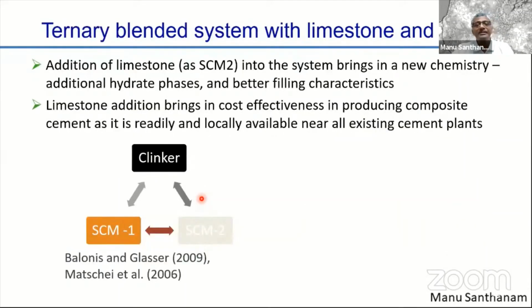Now, as far as the ternary blended system is concerned, that's where we believe limestone can have a major impact when it reacts with the available reactive aluminate from a secondary supplementary cementing material in a cementitious environment. That's when it leads to a very good synergy in a ternary blend and leads to the production of hydrated phases that are stable and can have a large effect on the strength and durability of the concrete.